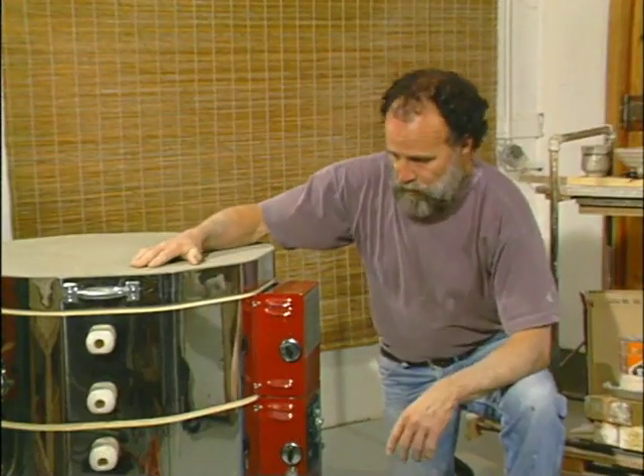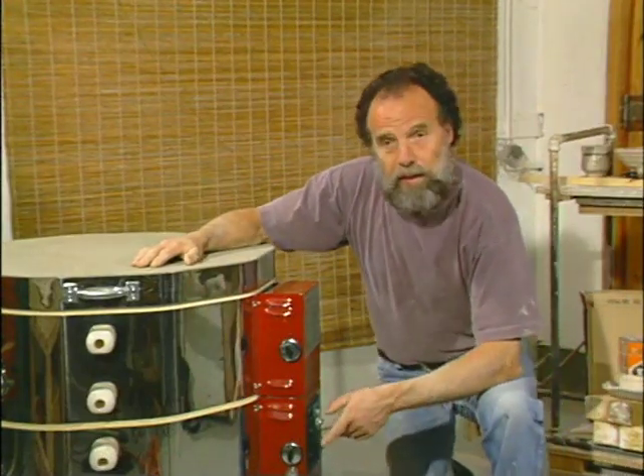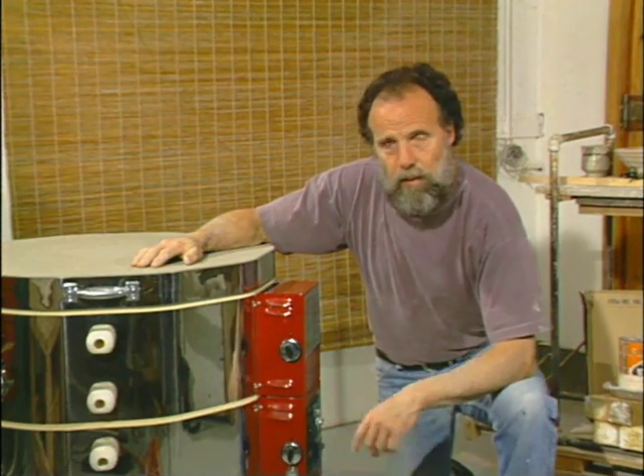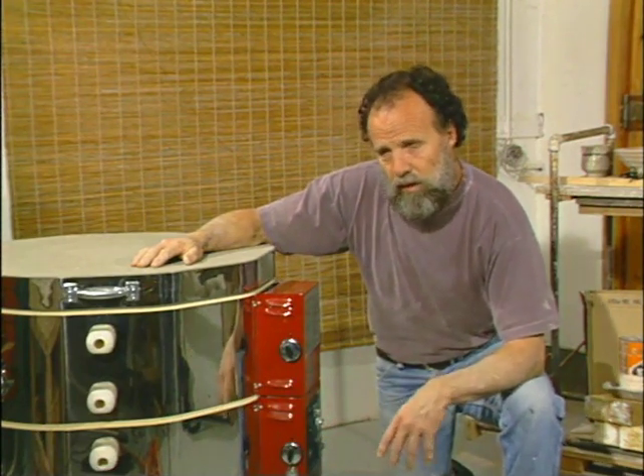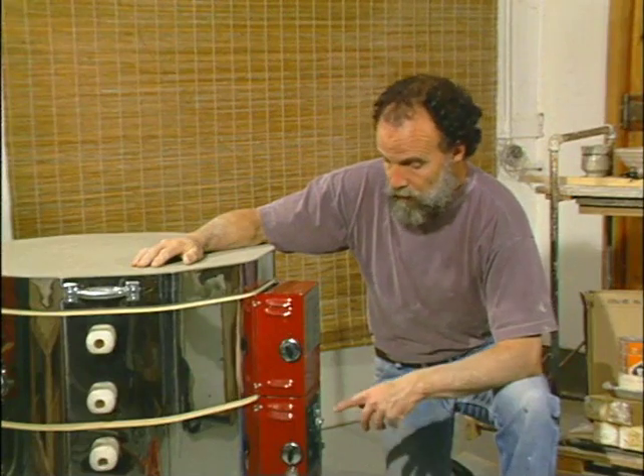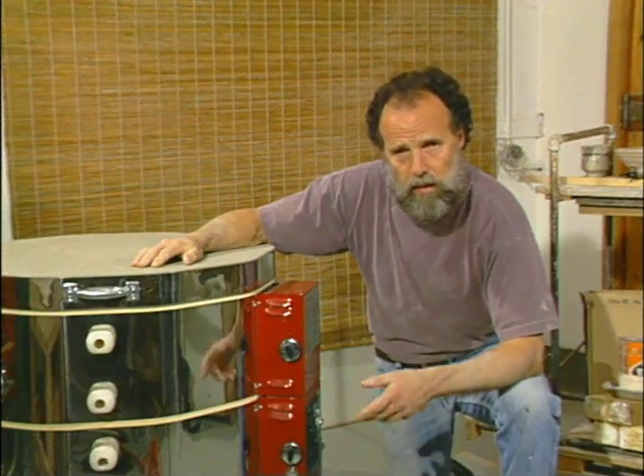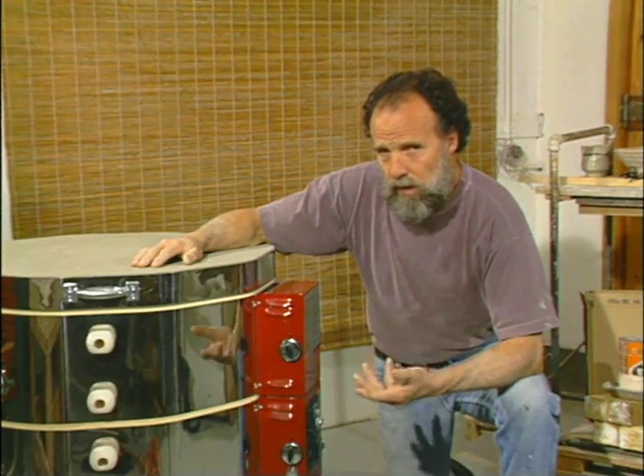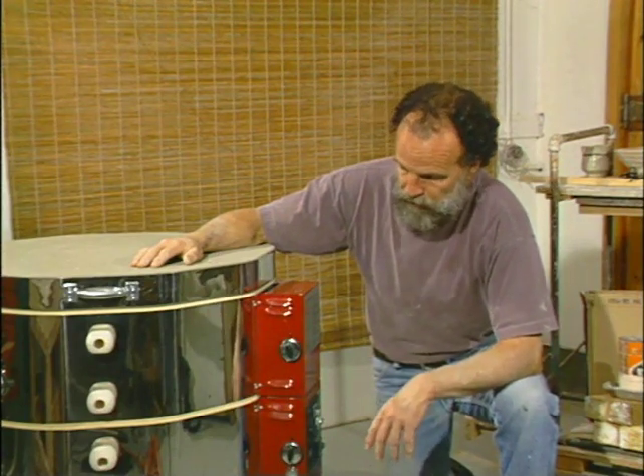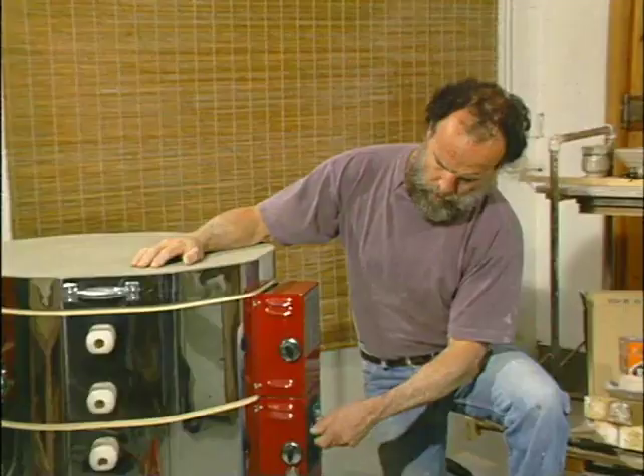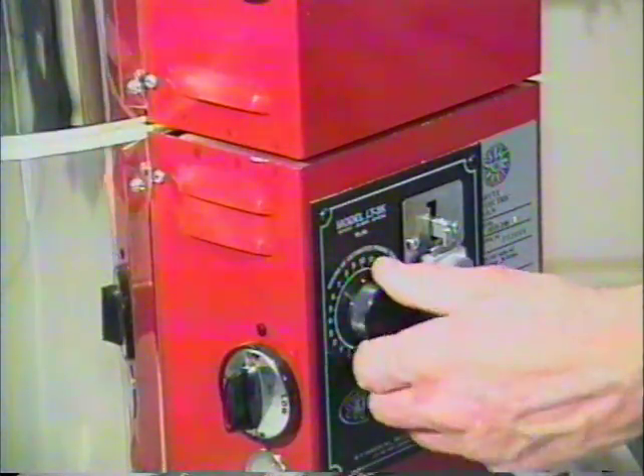Okay, we've got the EnviroVent switched on. Last thing we need to do is set the limit switch for the time. We can expect that the glaze firing will take a little less long than the bisque firing. We can go a little faster at the beginning because we've already fired this clay. We're not concerned about explosions due to moisture now. So let's set it for 10 hours.